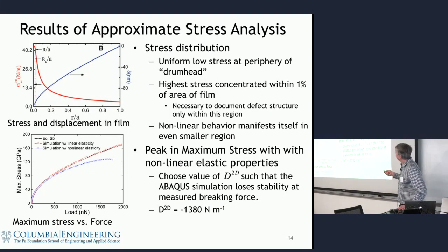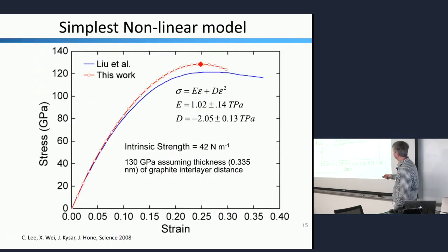Then we could get, for instance, stress as a function of position, and the maximum stress as a function of load. What you could see is, when you add this nonlinear term, you get a lot less stress at very high loads because you're getting weaker as you start to really stretch those bonds. So we found the maximum force that fit our experimental value, and we got a d of minus 1380 newtons per meter, which gives you a stress strain curve that looks something like this.